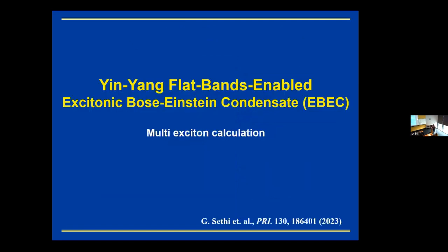With that singlet calculation, I want to comment that many DFT calculations, when they make the prediction on excitonic insulator states, stop here because it's very hard to do multi-exciton density functional or GW calculations these days. So many people just say, I predict an excitonic insulator state, and potentially excitonic Bose-Einstein condensation. However, to really confirm exciton Bose-Einstein condensation, you have to do the multi-exciton calculation, which my graduate student spent 2 more years after publishing that paper to do, as the second work.